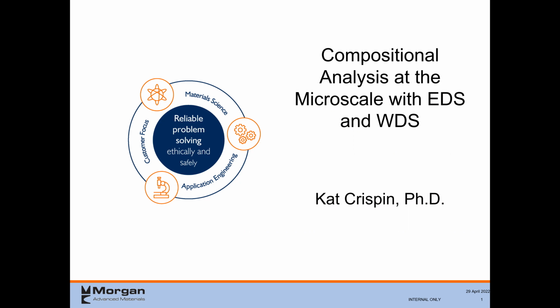And the same holds true for doing quantitative EDS versus quantitative WDS. It takes a lot longer. So, people that just need ballpark ideas, EDS is fine because it's quick and it's easy. With WDS, you're looking at spending a minimum of an hour or more, depending on the level of detail you need. For instance, just the setup alone, with the standards, is probably close to an hour.